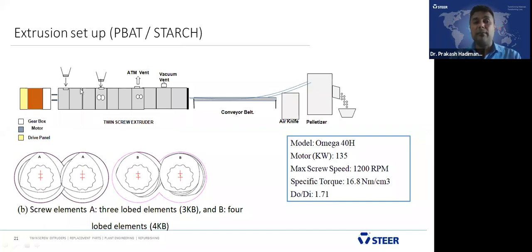This was the extrusion setup we have used, an Omega 40H, 135 kilowatt, maximum screw speed 1200, and the specific torque was 16.8 and Do/Di 1.71. And we have used both technologies, standard and FGT technology. We collected all the samples and extruded, and finally that sample was fabricated by injection molding into specimens. We did the characterization. In the next slide, we are going to discuss the characterization.